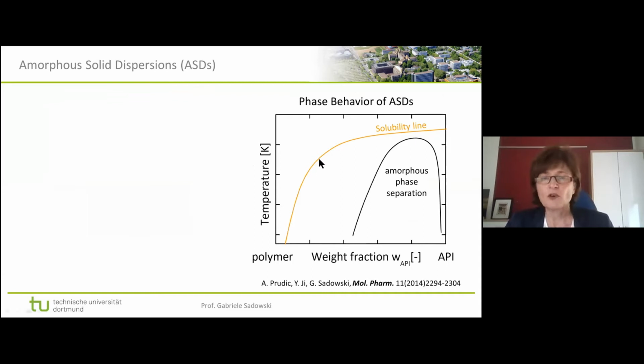To know whether it's stable or not, as a pharmacist, we look at phase diagrams, of course. This is what you are also used to. The phase diagram we are interested in in this case is a binary mixture of the polymer and the API, as a function of temperature. There are two lines which are of most thermodynamic importance. This is the solubility line, the orange one, and you have the black line.